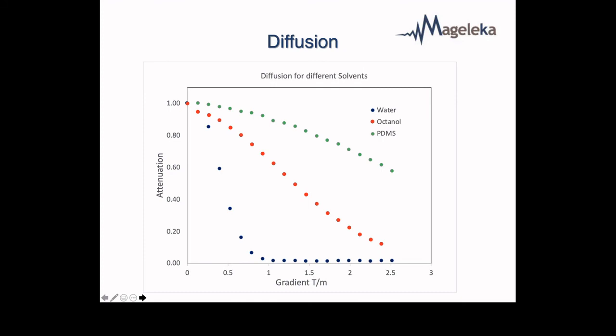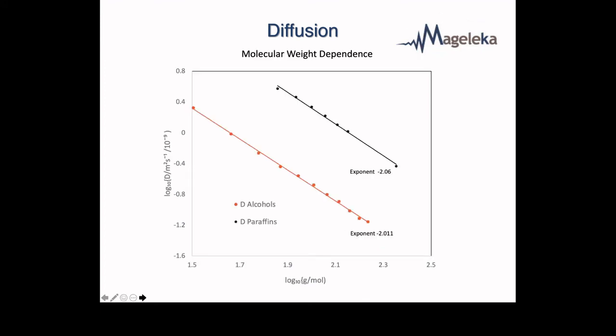So just some other things. You might be interested in different liquids. So this is water. And again, the time constant, well, it's a Gaussian function in this case, but the time constant for water tells you that the diffusion coefficient is a large number. If we go to octanol, a much bigger molecule, it's slower. And if we go to a polymer liquid, it's slower still. And so we can measure the diffusion coefficients of bulk liquids and solvents, molecules, polymer solutions, gels, and they all have very valuable structural information.